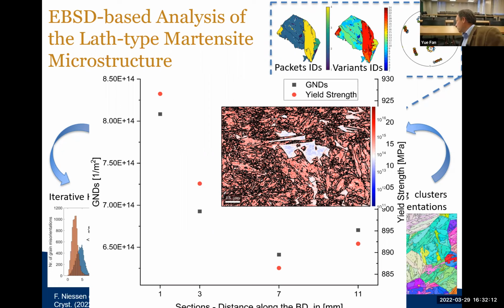Now, of course, you have to consider how much delta ferrite phase you have and what the rest of your microstructure looks like. If somebody wants to see the rest of all this put together, I can obviously show you later. But it's really remarkable that you can see, as a function of build layer, you can change the microstructure, get different properties, and you control it and do that in a targeted fashion.